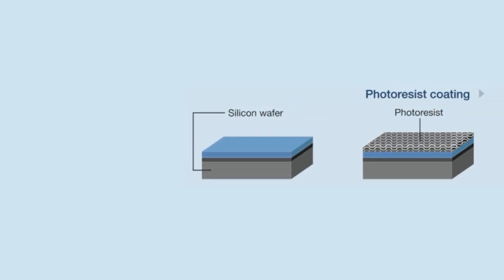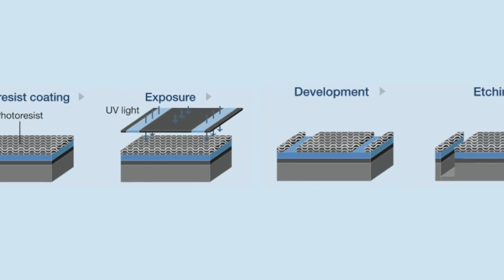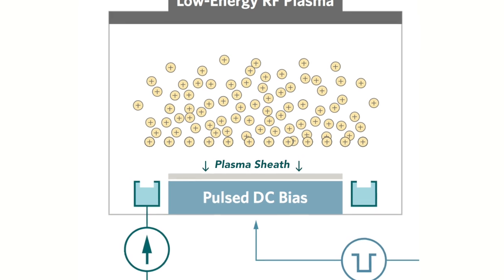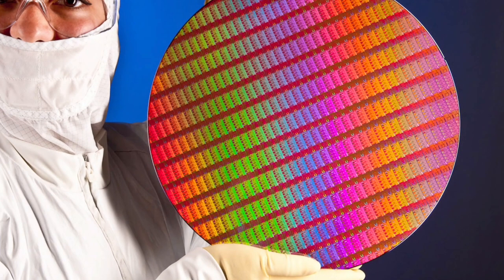In semiconductor processing, we want to drive chemical reactions on surfaces that remove silicon, so we use halogen plasmas to do that. An important property of low-temperature plasmas is the sheath — a thin skin of high electric field between the plasma and the surface it's contacting, that directs ions perpendicularly towards the surface. That allows us to dig very high-aspect ratio, precise 20-nanometer order holes in silicon that are used to print the wires necessary for circuits.